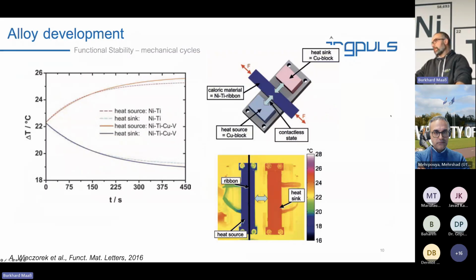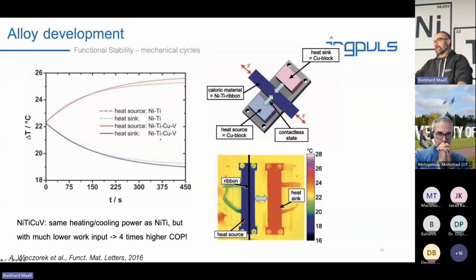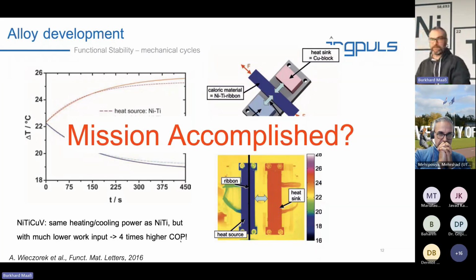This was during a research group with the Seeleke group, and they put this in their elastocaloric characterization machine. And what they found out was that the elastocaloric behavior of both materials was more or less the same. However, the work needed for the quaternary material was 4 times lower. So we get a 4 times higher COP, which until today makes it a very promising material. So we could say, okay, we're done there. We have made the best material.